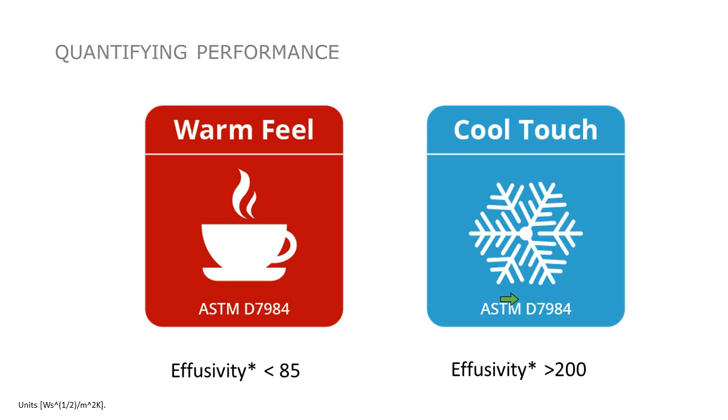So there is room for some adaptation here, but I do think it's helpful to have some anchor points or context for what qualifies a material as feeling cool and what qualifies a material as feeling warm. Generally, we're seeing consensus around under 85 for warm and over 200 for cool touch. If you're active in this space and interested in contributing to that discussion, I would love to hear from you. If you want to just enter a few words into the chat box on that interest, I'd be happy to revisit it with you one-on-one.